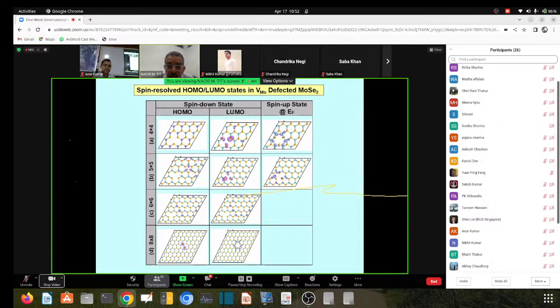We have plotted the HOMO states using VASP. This is a contribution by Watha. So we could see that in 4x4 and 5x5 there is delocalization in the spin down. We plotted HOMO because it's a semiconductor, and the upper spin up is conducting. We can see here they are delocalized, but the state starts shrinking with increasing size of the sample, and we interpreted that as due to the ferromagnetic interaction with the images of the vacancy.